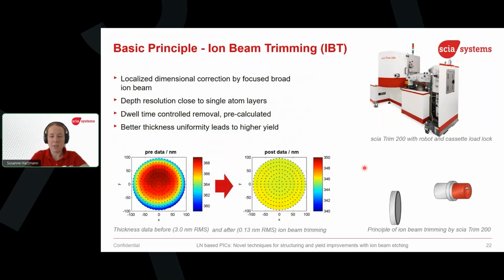In ion beam trimming, we see on the right-hand side, on the upper part, the machine that can be used to do so. We have a load lock at the front where a wafer cassette can be placed with 25 wafers. Then there's a transfer module where the wafer is handled in and the notch or the flat is aligned. And then we have the main chamber here. At the bottom, we see how this actually works. So the ion beam has been focused on a small area of roughly 1.5 centimeter diameter in size, and then it's raster scanned along the wafer. Now we can control the dwell time to control the removal to have a uniform pattern afterwards.